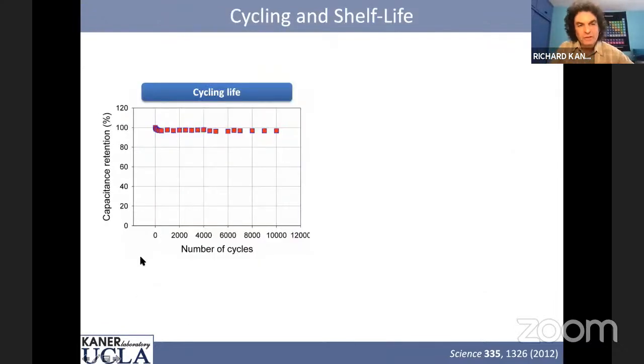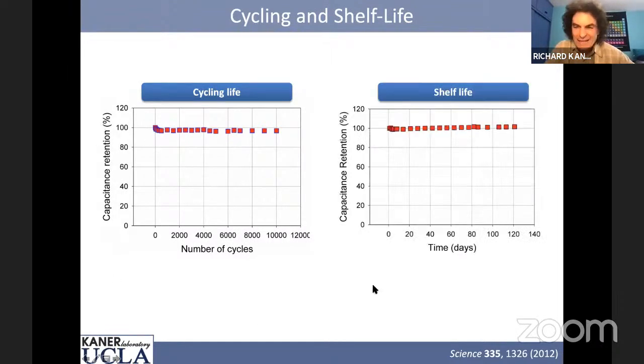They have very good cycling life. Here's 10,000 cycles. You can see they have very high capacitance retention. Here's their shelf life. They look pretty good. This is about 4 months. And so they're quite stable.